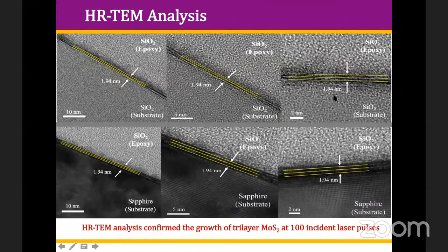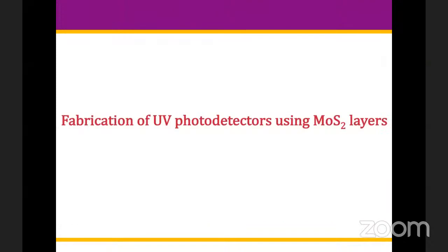So if you see, 0.65 multiplied by 3 roughly comes out to be 1.9. That clearly shows that trilayer MoS2 has been successfully made, and the interface is very, very sharp, which clearly shows the advantage of pulsed laser deposition over other techniques in making a very good interface and very good quality MoS2.